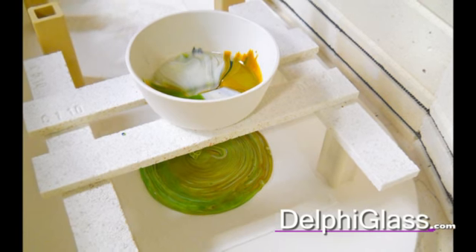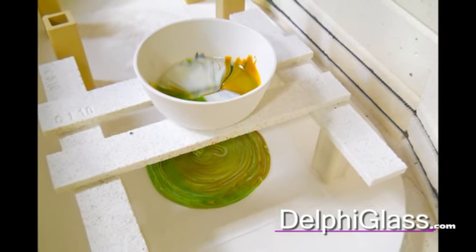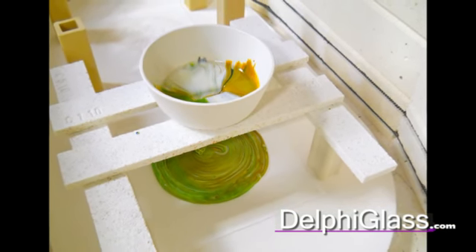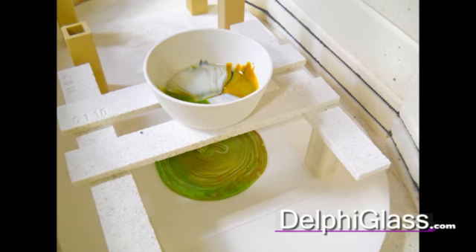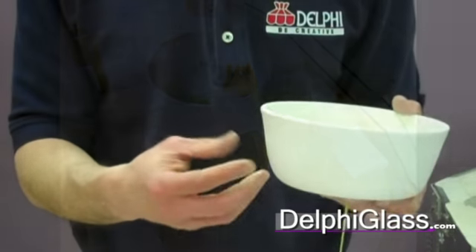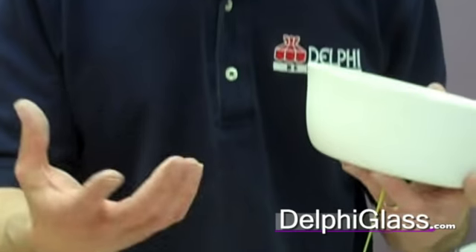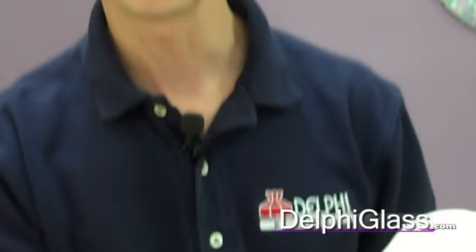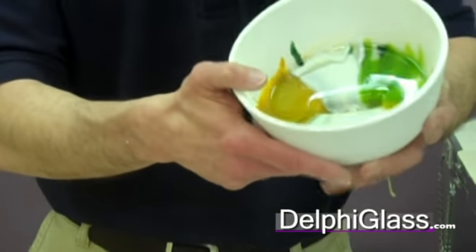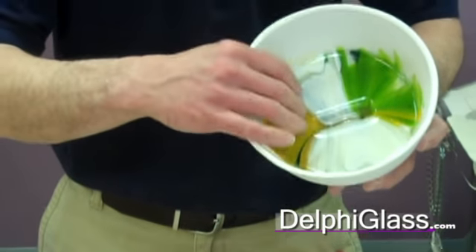You don't want to go too fast because you can actually thermal shock the pot a little bit. So, 400 or 500 degrees an hour is plenty of time. I take them up to 1600 degrees. You want the glass to be fairly fluid so it'll come out. You can see how we've left all the little tails on these as they drip out. And you can see that there's a little bit of glass left in there, but there's not a lot of glass.